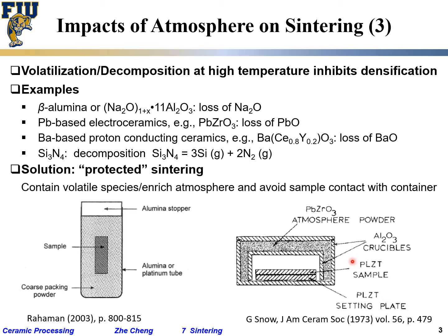And then they put an alumina crucible, and in between them they put lead zirconate, which essentially provides you a lot of lead oxide so that the lead loss from the sample of your interest is reduced. Even doing that, you cannot avoid complete loss, but at least not 10% loss. I'm losing maybe 0.5%, 0.1%. Make sense? You're just doing something to try to make it lose less.